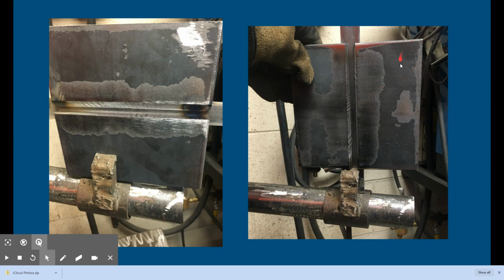Here would be my 3G if this were a 3G setup. It's not stamped yet. It's just kind of hanging out there. I'm holding it for the picture, but I would have a 3G stamped up in the upper corner right here. And again, I wouldn't clamp this one in here. I'd clamp it up higher so that they can actually start on the backing strip and work their way up. Use that backing strip to kind of preheat things as they go. Same thing you can see in the 2G. They're going to start welding out here on the backing strip to get that nice and hot before they tie into their weld and make it out, and they can run out on the end.